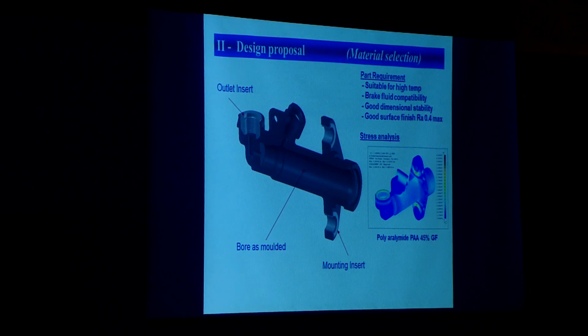The second stage was the design proposal. The part requirements were identified clearly at this stage. It should be suitable for very high temperature. Continuous use temperature was fixed at about 140 degrees centigrade. It should have very good brake fluid compatibility, very good dimensional stability, and a very good surface finish, especially inside the bore. And this surface finish should be attained as molded, not by any secondary operation. It should be as molded. This was a very major challenge.